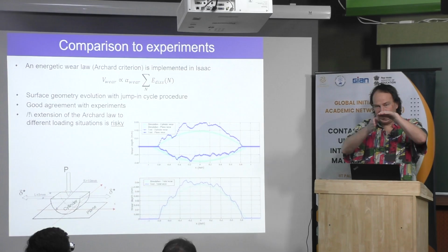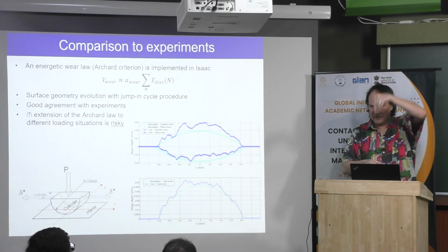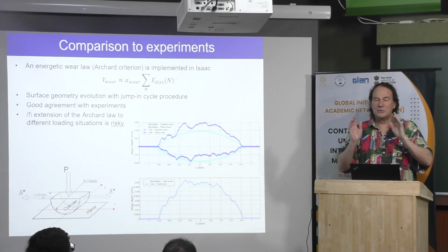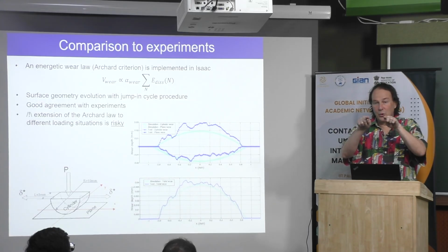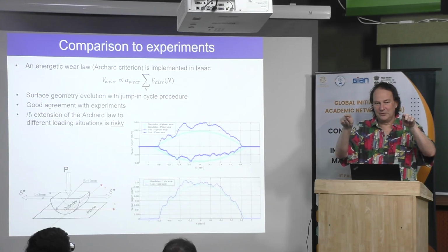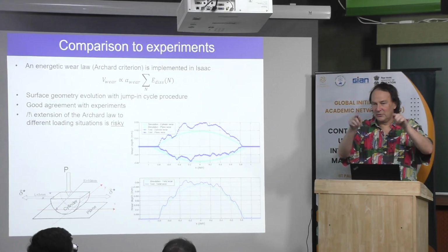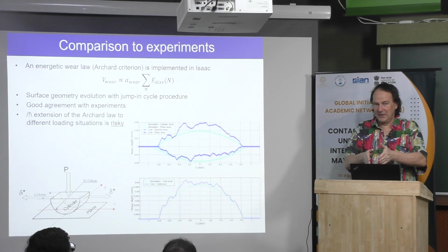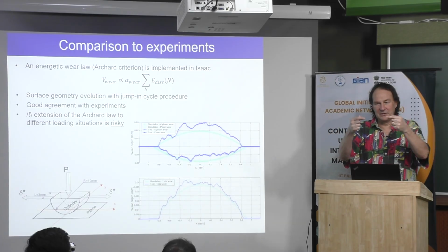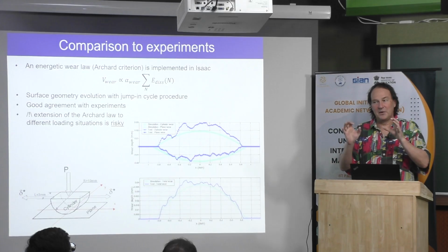When the machine is vertical, it means that the movement is vertical. And one of the keys was to open the contact very often, for example, each 1000 cycles. So you open the contact, all the debris fall down, and you reinstall the contact. Then you can do a simulation and you can do an experiment without wear debris.